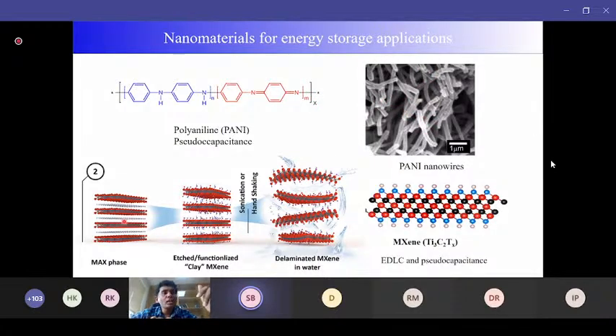And there is another new entry in this field. This is known as the MXene, where the main material is the MAX phase, where there are some carbide layers of titanium, vanadium, or other carbide layers. Those carbide layers are connected by aluminum. Now, if this interlayer aluminum is selectively etched, it leads to a layered, clay-like structure, and they can be exfoliated like a graphene exfoliation. They can be separated into individual layers.